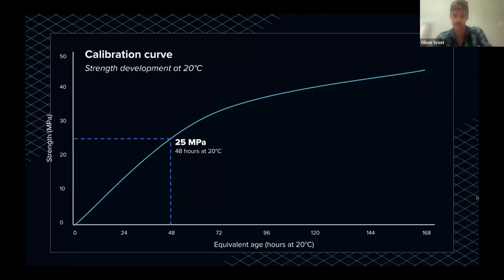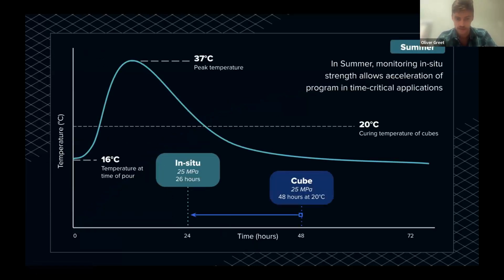Now, coupled with sensors being cast in situ, we can place those into the element itself and see how warm or cool the element is, which is really going to be dependent on how thick the element is, as well as the seasonality, so the effect of ambient temperature conditions. And we know, using that temperature information, how fast or slow the concrete is actually moving along its calibrated curve, and when we're going to obtain that 25 megapascals.